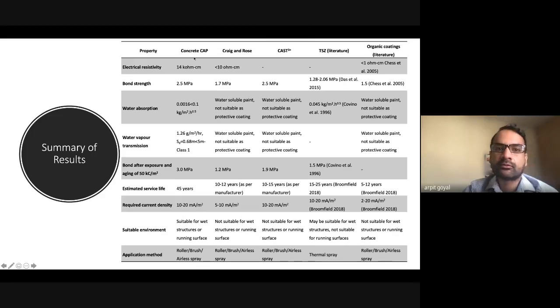No, so basically this concrete cap is our paint. This is the commercial paint which is already available in the market. So these are basically the coating anode systems. Coating systems mainly fail because of the weakening of the bond between the paint and the concrete structure. That's the main failure mechanism of any coating system. So we found that the coating system we developed has much higher bond strength than any available coating anodes in the market currently. And even after aging it to 50 kilocoulomb charge, its bond strength is much higher than any available systems.